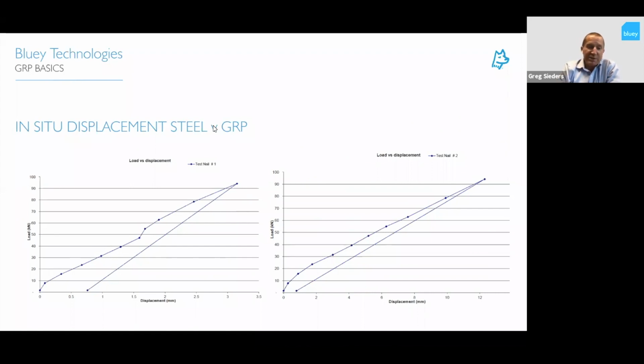So this is a side-by-side test we had carried out. On the left-hand side is showing the steel deformation. So having a higher modulus, you're only getting about 3 mm deformation in your free length. In a GRP, you would expect to get 3 or 4 times that in your free length. But when you return back to your datum point of 0, you can see both of them only having about 0.7 mm of deformation, which is all your grout soil interface.